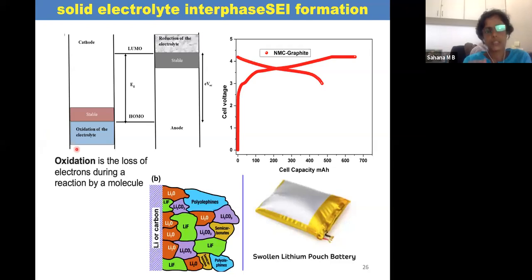So in most of the cases, this diagram I think you would have seen earlier. The center portion of that gives the relative energy of the highest occupied molecular orbital of the electrolyte and the lowest unoccupied molecular orbital of the electrolyte. And this is the anode chemical potential. The anode chemical potential to begin with will be higher than the LUMO, and the chemical potential of the cathode will be smaller than the HOMO of the electrolyte. In this situation, there is a reduction of the electrolyte near the anode and the oxidation of the electrolyte near the cathode.